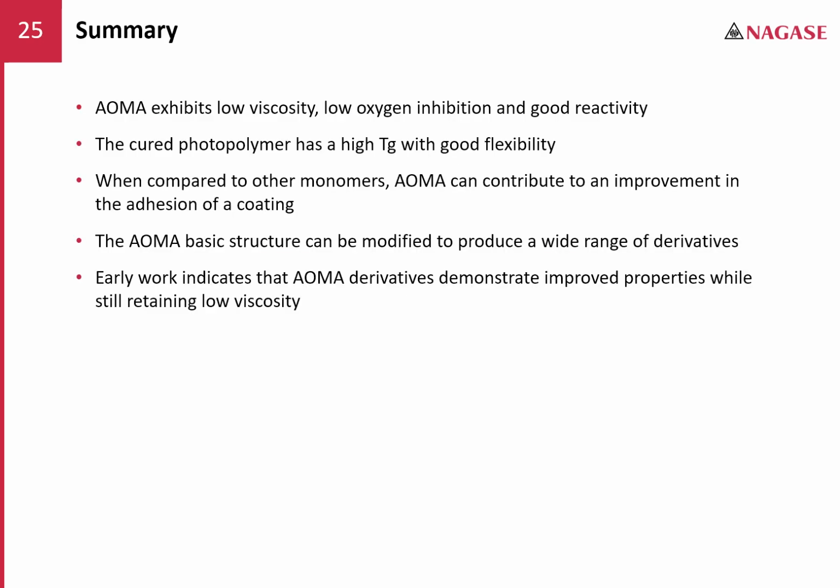So I'd like to summarize what we've discussed during this presentation. AOMA exhibits low viscosity, low oxygen inhibition, and good reactivity. The cured photopolymer has a high Tg with good flexibility. When compared to other monomers, AOMA can contribute to an improvement in the adhesion of a coating. The AOMA basic structure can be modified to produce a wide range of derivatives. And early work on these derivatives indicates that they demonstrate improved properties while still maintaining low viscosity.